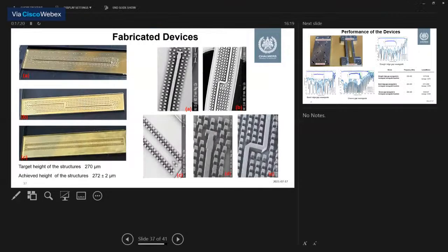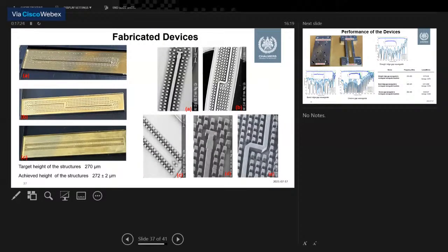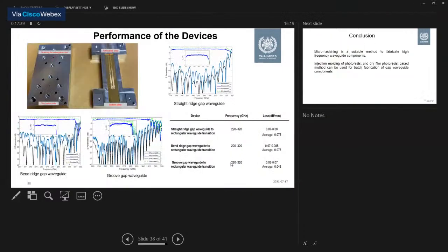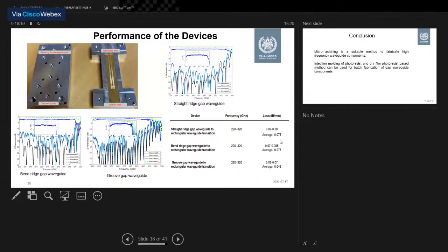That's why we fabricate some gap waveguide transmission lines by this SUEX photoresist. So the target height was 270 micron, and as you can see, the achieved height was 272 micron. From the measurement result, we see that it has very good agreement with the simulation result. And we actually fabricate three different types of transmission line. For straight ridge gap waveguide, insertion loss is 0.075. But for the groove gap waveguide, which performs similarly to a rectangular waveguide, the insertion loss is 0.048 dB per millimeter, which is actually similar to the conventional micromachining methods.